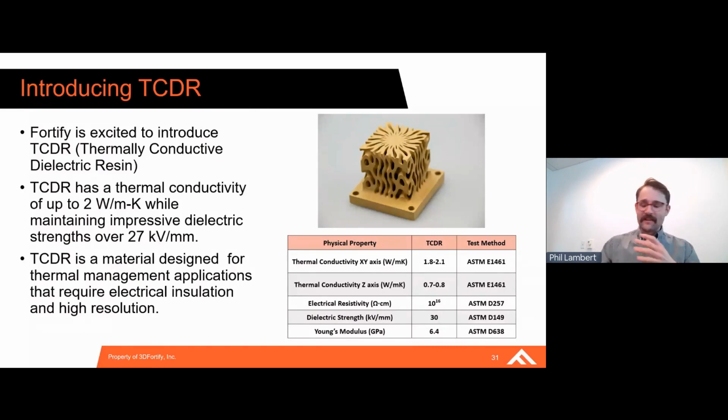And I just want to highlight that throughout that whole screening and formulation design process, we're always probing the photokinetics. We're always running those slot working curves and build plate adhesion tests, making sure that the formulation we're dealing with, besides having a manageable viscosity and a desirable thermal conductivity, is also able to achieve the depth of cure and the scatter behavior that we need to meet our application requirements. And again, as I said earlier, in this case, it's products like electronics heat sinks and cold plates.